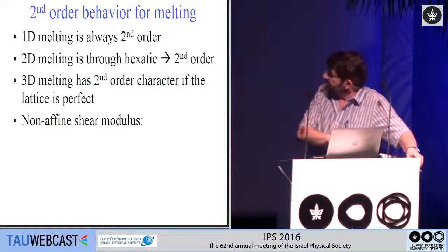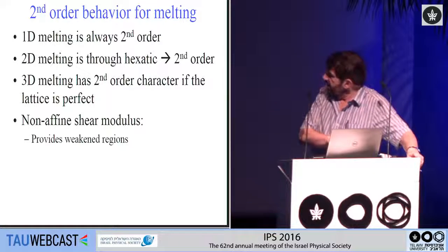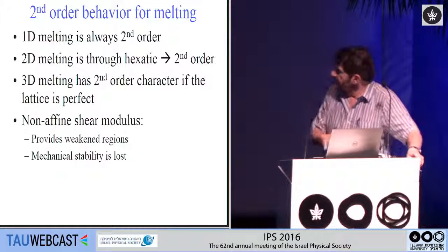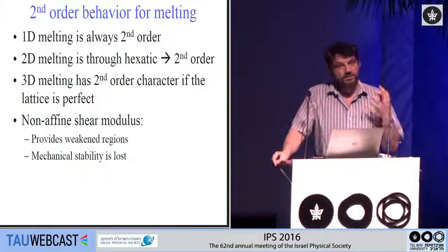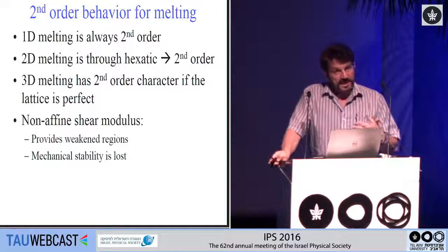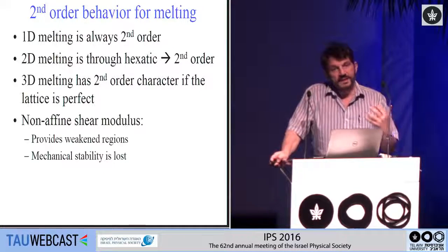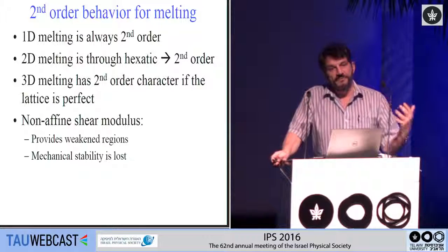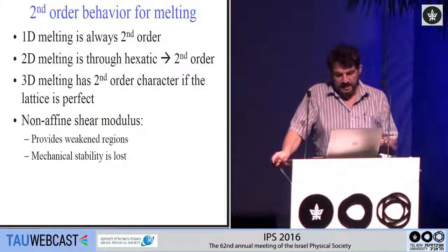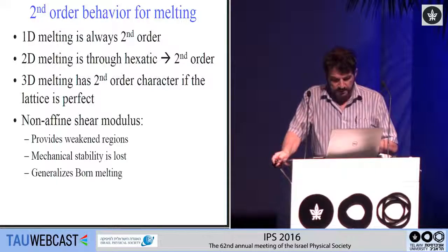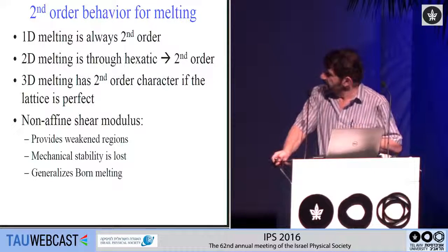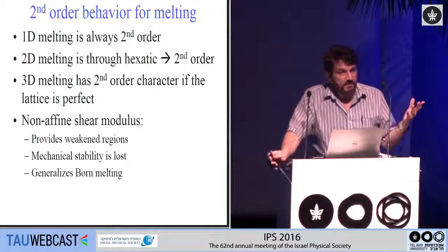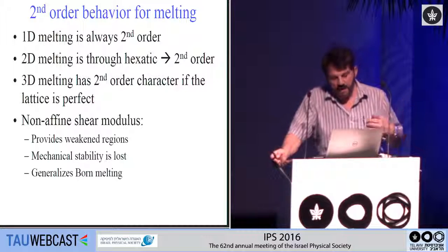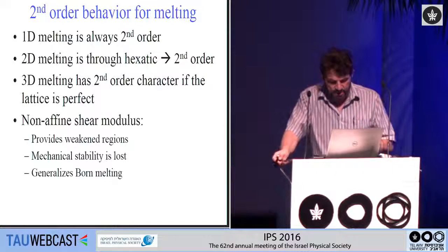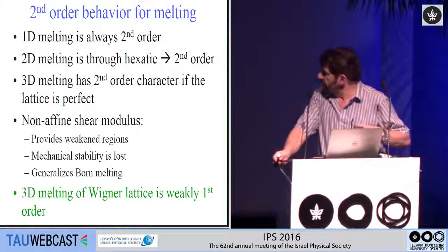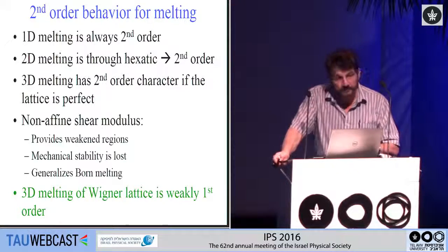And so it's the non-affine shear modulus, as I said, that really provides the weakened regions, and it's this that's driving the melting. And this is what's leading to the catastrophic failure of the elastic transition that was first predicted by Born many years ago. It's sort of a generalization of Born melting. If you want, it gives you more intuition about the nature of Born melting.